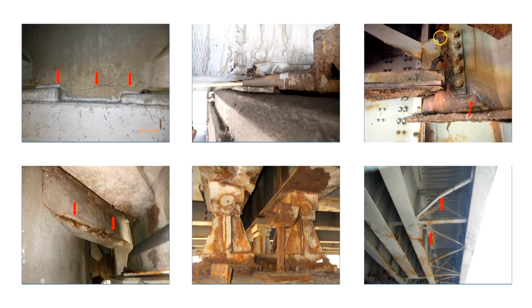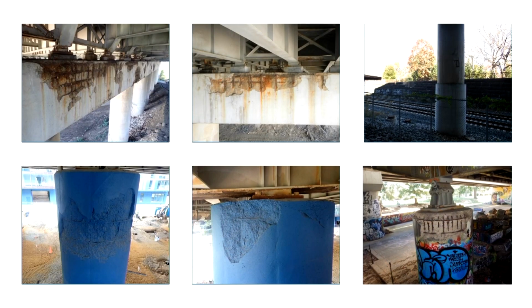All right. Steel and concrete diaphragms exhibit deterioration, whether it's corrosion or cracks in them. And then you have steel bearings with signs of deterioration, and also some elastomeric bearings that show the same sign of deterioration as well, and they need to be replaced. As you can see from these images, we have pier caps that have delamination and corrosion of the steel reinforcement, and columns with delamination and spalling as well that need to be repaired. Now I would like to hand it over to Jeffrey Hollands to talk about some of the state-of-the-art solutions we're providing for this project.